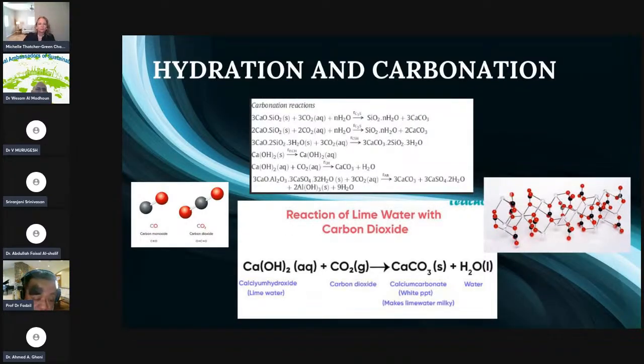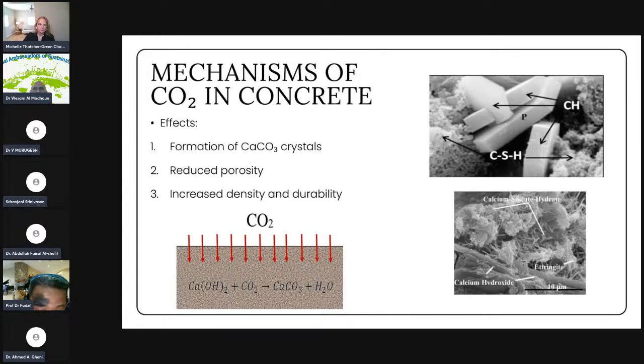Before we talk about CCUS, I just want to give some ideas on what is happening in the concrete. Previously we had an issue where, in concrete technology, the hydration process produces calcium silicate hydrate, and at the same time the hydration process also produces calcium hydroxide. This calcium hydroxide occurs in the plate phase, and unfortunately, the calcium hydroxide stops the intersections of calcium silicate hydrate and creates micropores inside the concrete matrix or the cement matrix. This issue has become a big worry to all the engineers and scientists, and they are looking at how to reduce the composition of calcium hydroxide in the cement matrix.